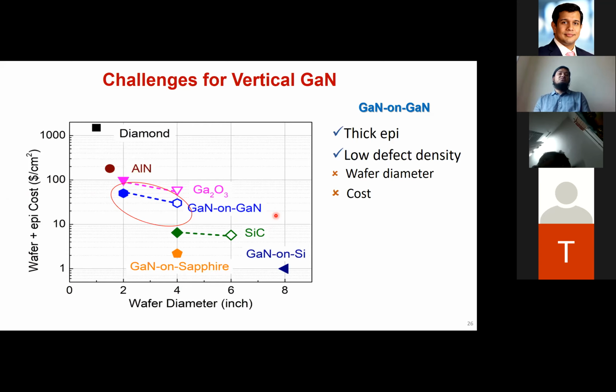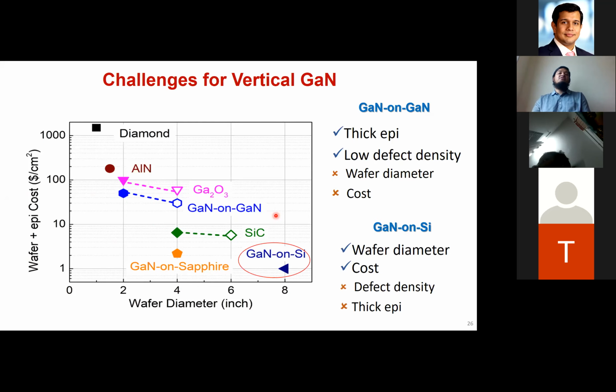So we have a second option. We can also grow gallium nitride on silicon. As of today, we can do 8-inch gallium nitride on silicon at a very low cost, almost 2 orders of magnitude lower than GaN on GaN. However, we're trying to grow gallium nitride on a different semiconductor, and here comes a lot of material-related issues. If we grow gallium nitride on silicon, we have a lot of defects that lower the device performance, and we cannot grow the thick gallium nitride that's required for higher blocking voltage.